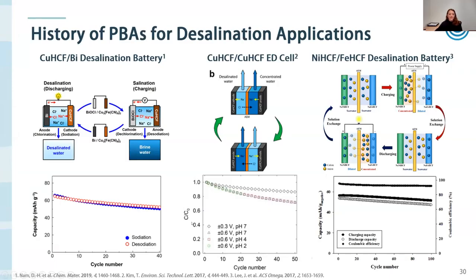This plot on the left is actually one of our previous papers where we looked at using copper hexacyanoferrate, and we saw capacity fading within about 40 cycles. Here are some other types of desalination cell configurations that used Prussian blue analogs, and you can see in all cases capacity fading occurs within just tens of cycles. Long-term stability is really important for any real-world application, including water treatment. And so this idea that Prussian blue analogs are degrading over time was kind of discouraging.